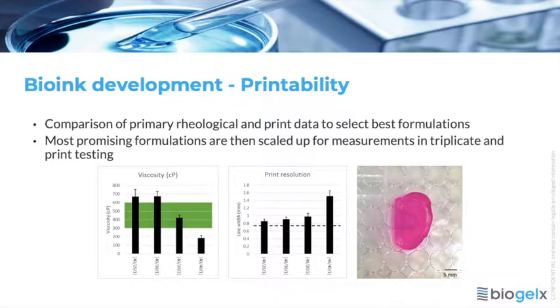The most promising formulations then were scaled up, and we were able to repeat these measurements in triplicate to give us some confidence that these were real results. And in this instance, you can see the first bar on both the viscosity and the print resolution test give the best results. The dashed line in the print resolution test was a peg-based bioink, which was used as a standard to compare the line widths to. And so that was the formulation that we eventually settled on, gave us this nice ear structure when we printed that to plan, and you can see that many of the details have been reproduced quite accurately here.